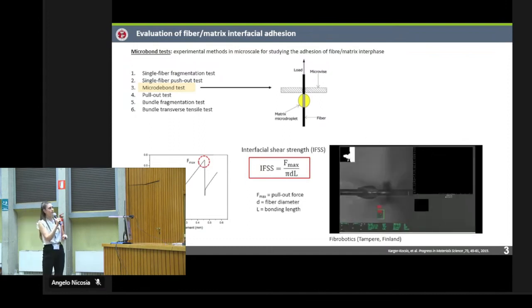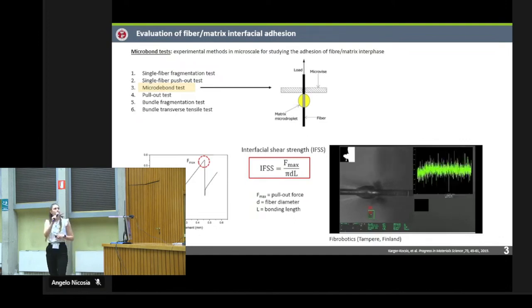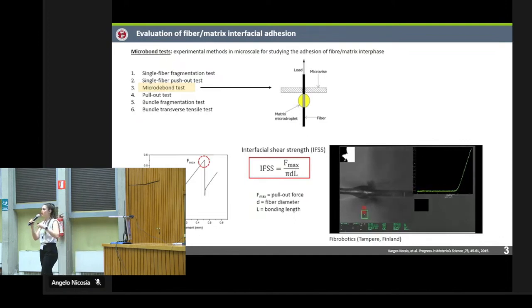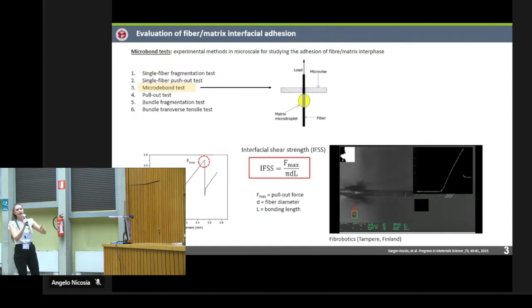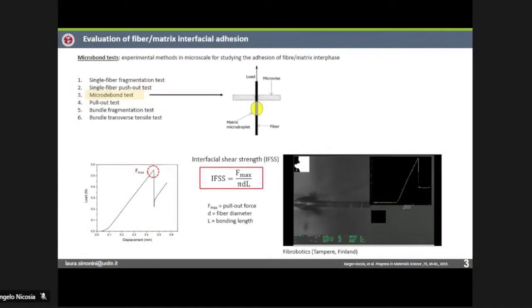In this video, the device takes the dimensions of fibers and droplets, then two blades come and reach the drop of matrix, so a shear stress is applied at the interface. It reaches a maximum value where we have debonding. Once we take this value and divide it by the embedded area, so the dimension of fibers and droplets, we can calculate the interfacial shear strength, which is the measure of adhesion between fibers and the matrix.